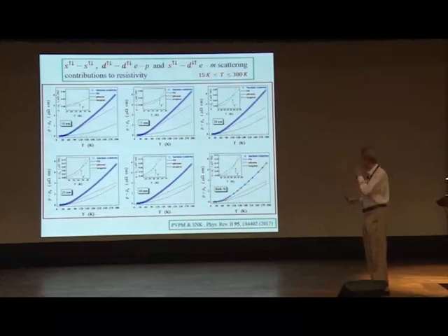And you can check that even with crystalline nickel. That is the bulk case I have put here for comparison. There is a temperature at which these two contributions are the same, the so-called T star. Below that, the phonon term is much less important than the magnon term. But then there is a crossover: beyond that temperature, the phonon term picks up more than the magnon term.